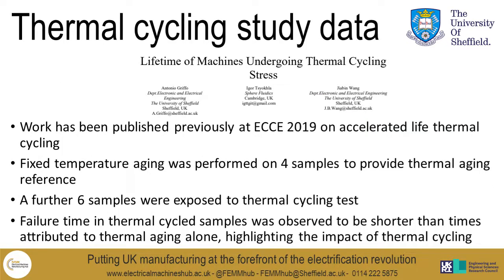So finally now I'd like to move on to the discussion about thermal cycling and how we can model that. So to start and give you a bit of context for this work, it's worth pointing out it builds on some work which was published at ECCE 2019 on accelerated life thermal cycling tests. In this work we had a number of samples. 4 of them were tested at fixed temperatures to provide a reference for thermal aging of the samples. A further 6 were exposed to different thermal cycling test profiles. It was observed in all the cycled profiles that failure occurred in a shorter time frame than could be attributed to the thermal aging alone, which highlighted the impact of the thermal cycling in this work.